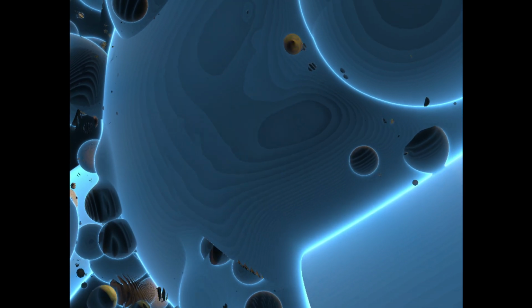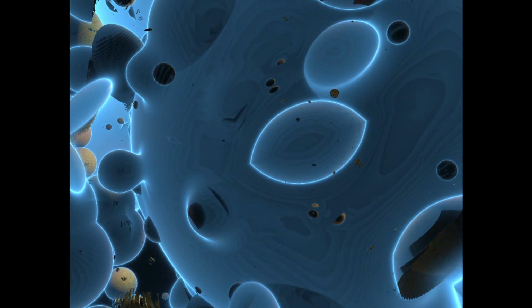This efficient scattering creates an instability in the system. An instability towards forming that spin density wave magnetic state. The system can lower its energy by developing magnetic order with exactly that wave vector. So the Fermi surface geometry actively promotes this type of magnetism. So the shape itself encourages magnetism. But you said earlier magnetism and superconductivity are often neighbors. Precisely, because that same nesting condition, mediated by those magnetic fluctuations, the little wiggles in the spin density near that vector, is also believed to provide the glue for the superconducting pairing. So the thing that causes magnetism also helps superconductivity.